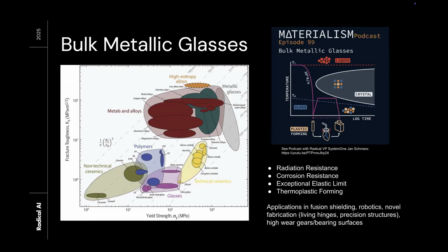So Taylor is in the audience. I will not try to explain everything about why bulk metallic glasses are interesting, but our VP of System 1, a professor at Yale, Jan Schroers, did a great podcast with Taylor where he'll explain some of this. But broadly, a metallic glass is made when, on this TTT time temperature transformation diagram, you cool at a critical rate such that you pass this nominal viscosity of 10 to the 13 before you have had a chance to nucleate any phase. And then you get lots of exceptional properties from the fact that you do not have a crystal structure.